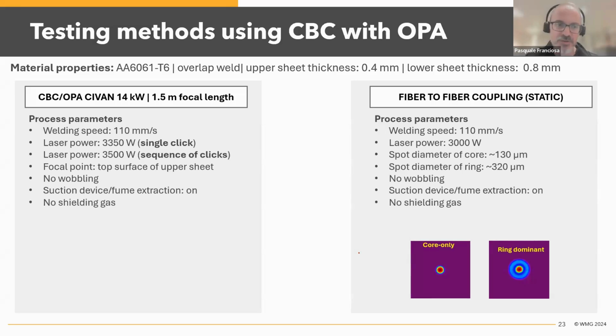Yeah, and this is what we did. So this basically is a comparison between the CBC technology from Civan. In this configuration, we are using the 1.5 meter focal length, which gives the smallest spot diameter on the workpiece, close to, let's say, 130 microns. Obviously, if you reduce the focal length, you will get a smaller spot. But in this project, we have used the 1.5 meter focal length.